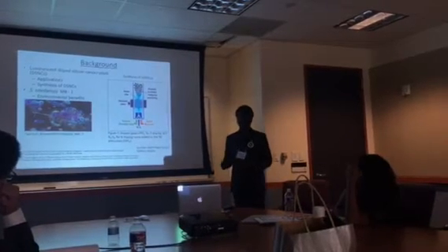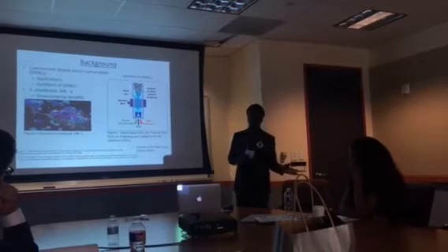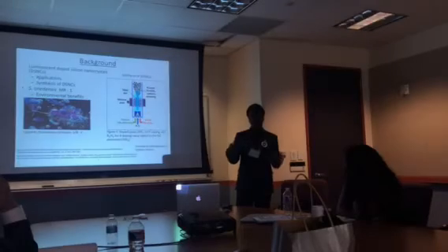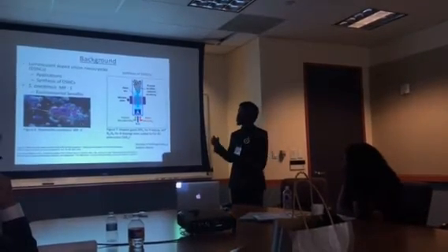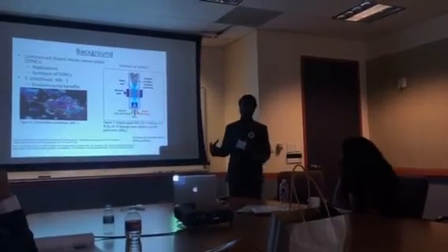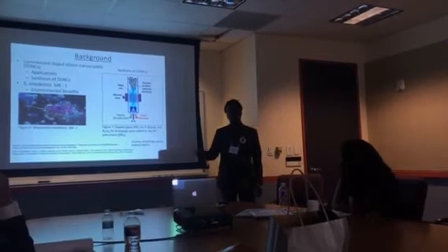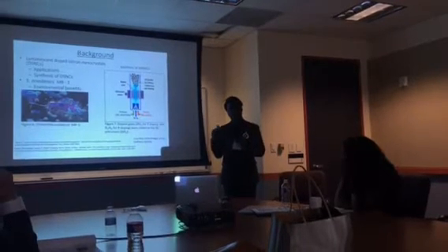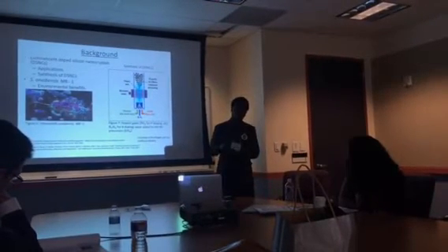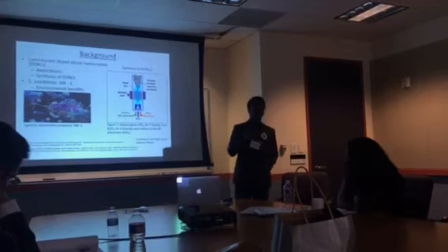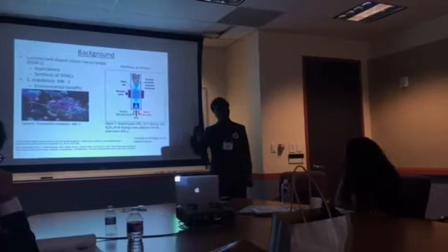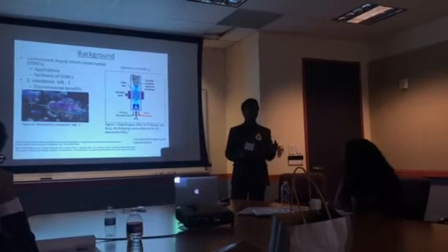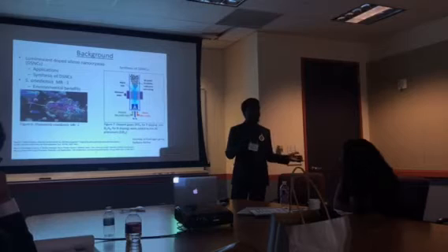Silicon nanocrystals and doped silicon nanocrystals are different. With doped silicon nanocrystals, we can use quantum confinement, as Andre mentioned earlier, to change the luminescence that we observe. If we change the size of the particle, we can observe different colors. However, when we dope it via N-type or P-type, we can keep the particle size and still observe those different wavelengths.